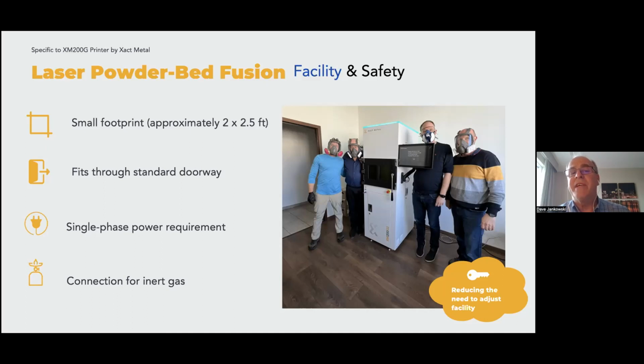It uses standard single-phase power, either 120 or 230 volts, depending upon the level of laser that you're using. We do use an inert gas, such as argon or nitrogen, to flood the chamber. During this metal laser powder bed fusion or micro welding process, you don't want to form any oxides. So this inert gas, argon or nitrogen, is injected into the build chamber and flows across the build plate. It ensures you don't generate any oxides during the actual printing process, which could detrimentally impact the properties of the component.